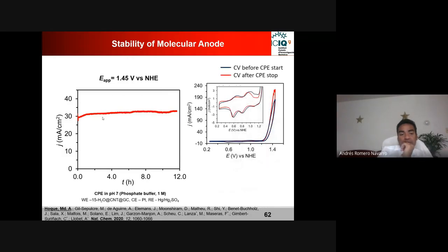Before I started and after I stopped, I was checking the cyclic voltammetry in order to check the stability and the molecular integrity of this system. So now you will see that we are getting a similar current, and you can see that the molecular integrity remained intact in the system. So what I got from this system is a current density of 31 milliamp, a turnover frequency of 8,000 per second, and a turnover number of 3 lakh.